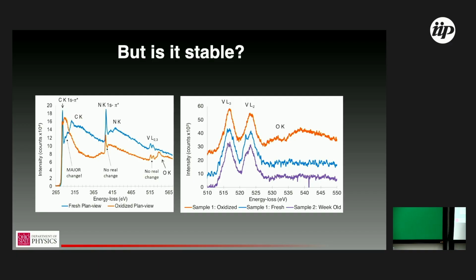And so this is a bit subtle, but if we look again at the blue curve, which is sort of the best data, you can see most clearly on this vanadium peak that there's this shoulder, and that shoulder is representative of high quality octahedral symmetry. And what happens is over time, or with oxidation, that shoulder relaxes, which tells us that that octahedron is starting to distort. So what this is telling us is don't let it see air.